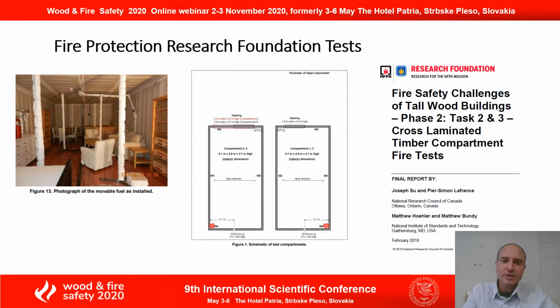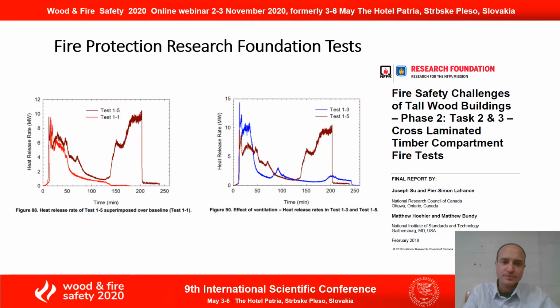And in this test, there were two different compartments. They were identical, except that one had a large opening factor and one had a small opening factor. And the goal of these tests was to understand the contribution of CLT to the compartment fire. And you can see the data, or some of the data here. So on the left, we have test 1-1, and in that test, everything was encapsulated in gypsum wallboard. Test 1-5, that was the same compartment with a small opening factor, but here one of the walls was not encapsulated with gypsum. And you can see at the beginning of the test, they're pretty similar.